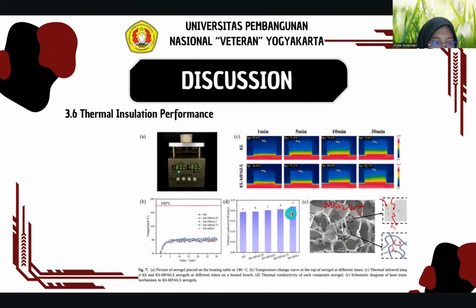3.6 Thermal insulation performance. Thermal insulation property evaluated by monitoring temperature change during heating at 180 Celsius in Figure A. Aerogel showed similar heat retention with the temperature difference between the top and bottom maintaining around 100 Celsius after 5 minutes of heating.